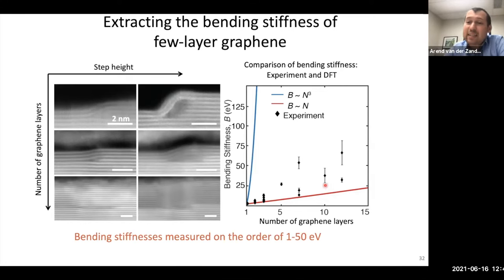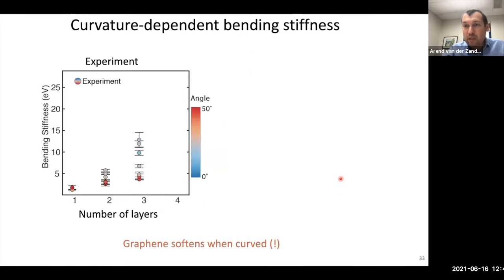And so what this data tells us is actually graphene behaves a lot more like a stack of papers than it behaves like a book, where all the values that we get are very close to that slip limit. Okay? But we did see something weird, where if you look at this data, it doesn't sit on this line, right? It sits above the line, and there's a lot of what looks like variations. What we realized when we plotted the data more carefully is that if we color coded our data by how much we bent it, actually the value varies.